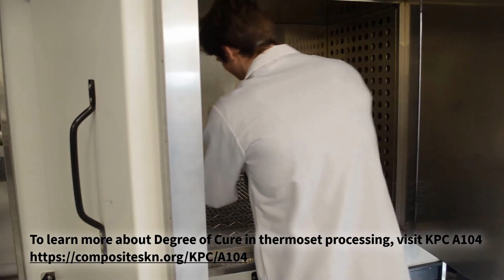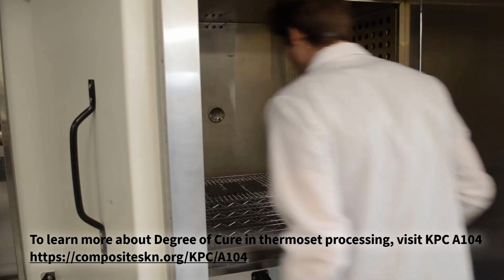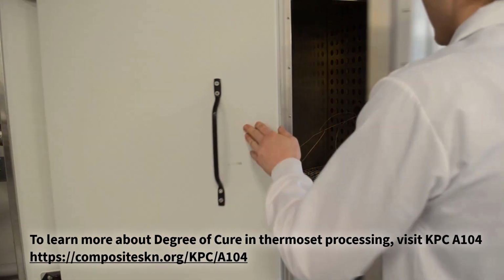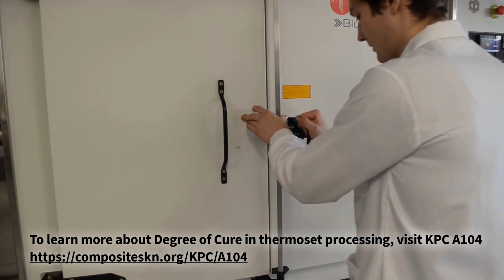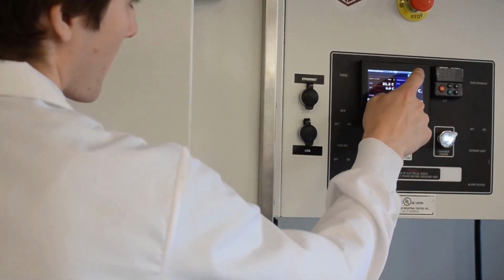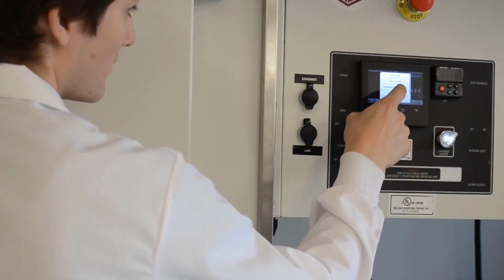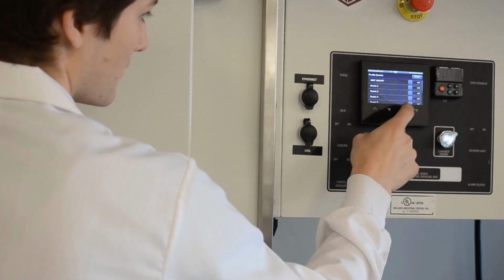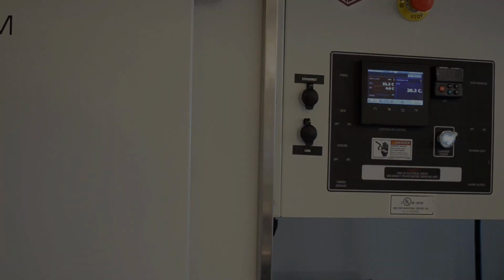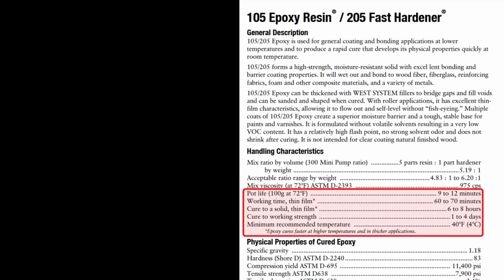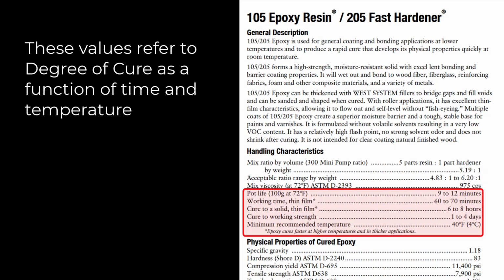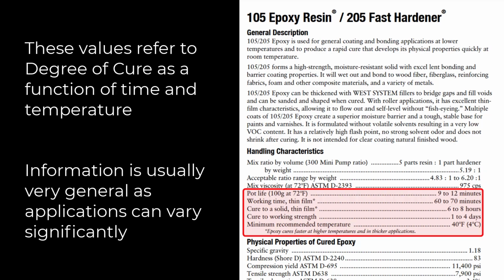The degree of cure of room temperature cured parts may be slightly increased by performing a heated post-cure in an oven. The effects of heated post-cures of varying temperatures and lengths are resin dependent. Some resins, such as the one we have selected, will continue to cure at a slow rate for weeks or months at room temperature, but can be accelerated to a high degree of cure with a heated post-cure. The manufacturer's recommended cure cycle, also known as the MRCC, is a good starting point to obtain a suitable cure.